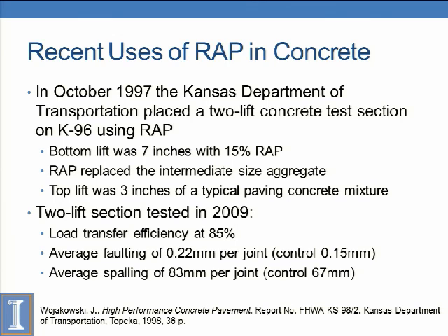But our suspicion is that with a fair amount of cement, we don't see an effect on the film thickness yet with the mixes we've tested. But you see an effect of the modulus. And I think that's why we focused on the fact that probably dirty FRAP and wash FRAP don't actually produce different results. Because it's a bonding issue, and if you have no bond for either one of them, then they affect the modulus the same way.